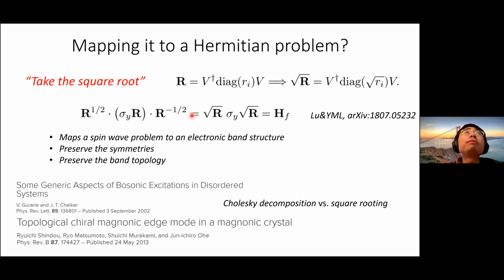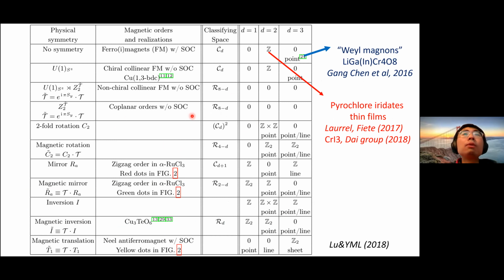So with the help of this approach, what we can do is obtain a table, not really a periodic table, but a table of topology inside a spin wave band. The reason is because we know the whole structure of the topology inside the electronic band structure. So after we are able to map the spin wave band into the electronic band, we are also able to obtain all the features in the spin wave band.